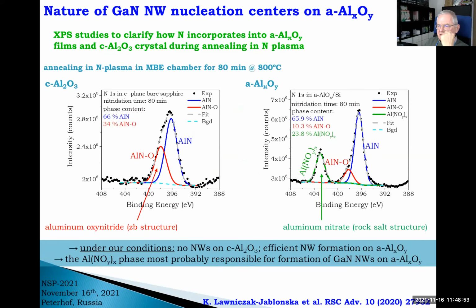And to be more precise, here I'm showing you the N 1s line of nitrogen from XPS, and this is crystalline sapphire exposed to plasma for 80 minutes. Here we see two signals. One is aluminum nitride, commonly observed, and the other one is aluminum oxynitride, which is also quite often observed. This crystallized in a zinc blende structure. But the surprise is here, because when we consider incorporation of nitrogen into aluminum oxide films, we see also aluminum nitride, aluminum oxynitride, but also an additional peak, which is aluminum nitrate, which crystallizes in the rock salt structure.